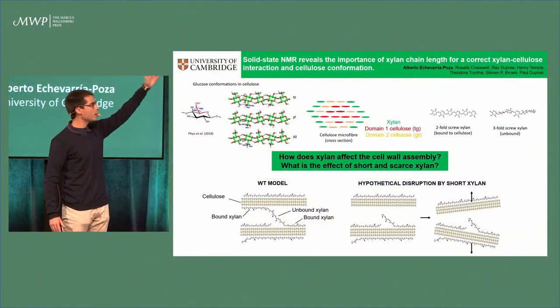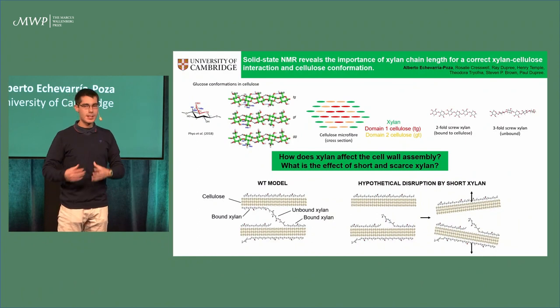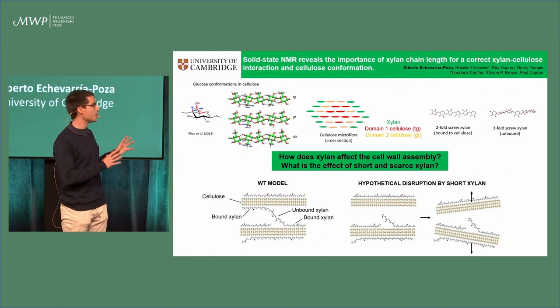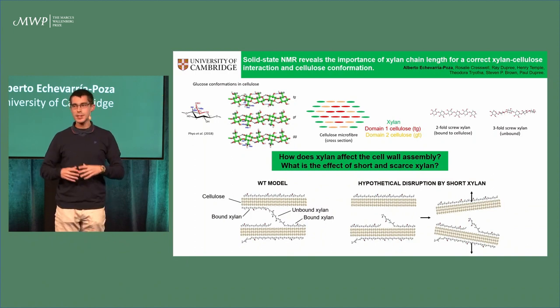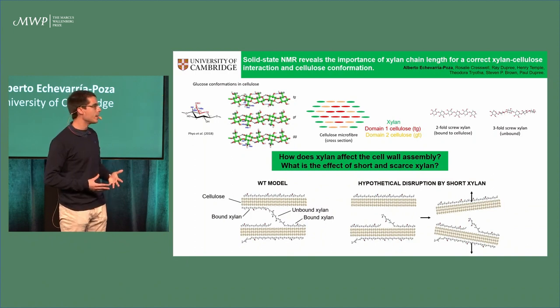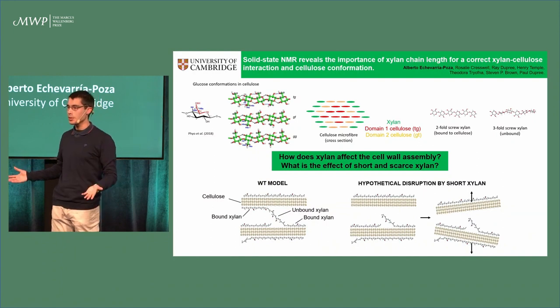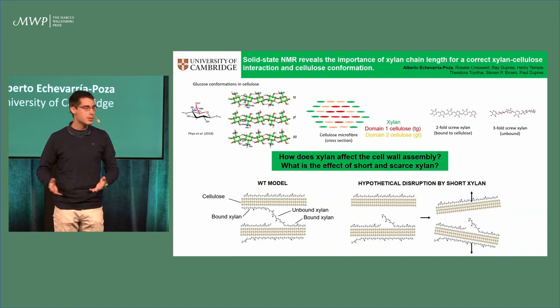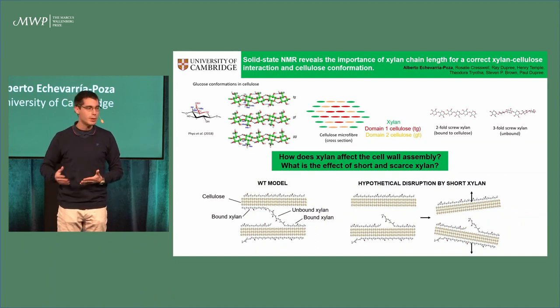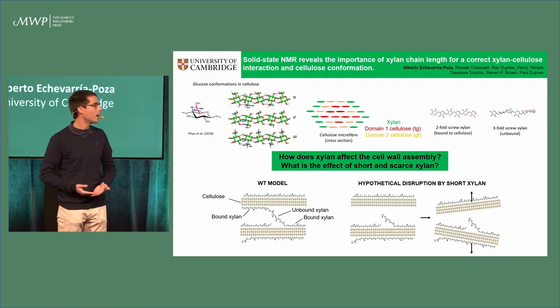If you have a look at the model in the middle, we can see that cellulose is actually a stack of 18 of these chains that we call a microfibril. Some of the chains on the inside adopt mainly one conformation, whereas the ones on the surface adopt a different conformation, what we call the main surface conformation. And then we would have xylan coating this cellulose microfibril.